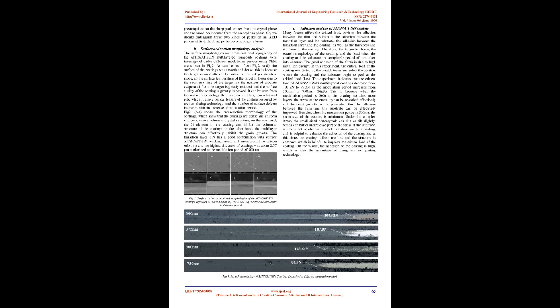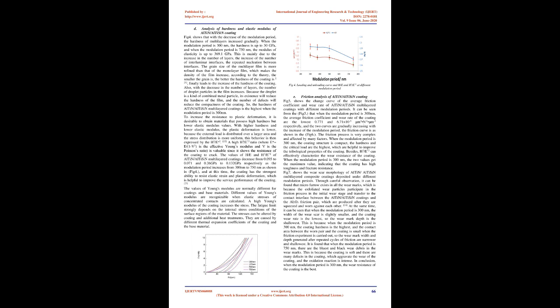For results: A. Phase analysis of AlTiN/AlTiSiN coating. As mentioned earlier, film crystalline and phase structure were characterized using X-ray diffraction, XRD, XRD-6100, Shimadzu, Japan. The scanning was performed from 20 degrees to 90 degrees at an incident angle of 1 degree.